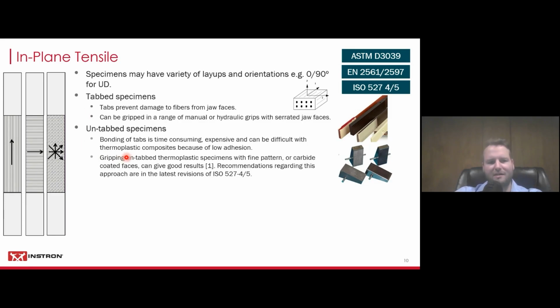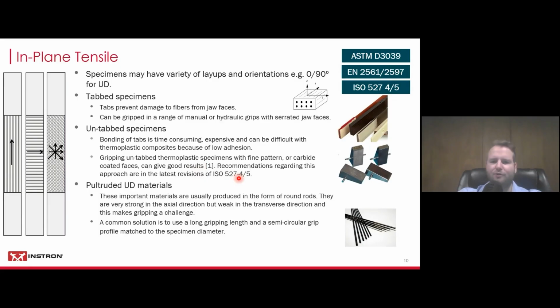But some materials, like we've established, a lot of you test thermoplastic composites, and they typically have a very low adhesion quality. They are chemically inert, and they have a couple other characteristics that make it really, really hard to bond things to it. So you might not be able to have any kind of tabs on thermoplastic composites. What we usually do there is we grip those with jaw face patterns that are very fine. We also use carbide coated faces, which can give you good results. And I also would recommend trying out simple sandpaper or emery cloth that you can use between your jaw face. Still, I would recommend a finer pattern, not necessarily serrated, and you use the sandpaper in between there to give you that grip so that your specimen doesn't slip, so you can get away with just enough initial gripping pressure, but at the same time protect your specimen from being cut into. There's also good recommendations in ISO 527-4 and 5 on this in the latest revisions.